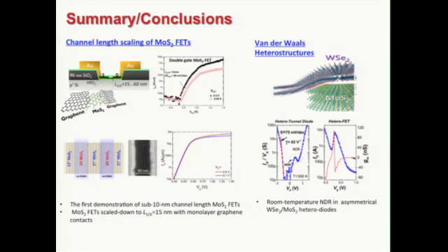I understand why the silicon curve is very steep as a function of channel length. Why with 2D material does it not? Because here, the point is that in bulk semiconductor, the dominant process is not the phonon, it is the dangling bond at the surface. So when you make it very thin, you don't have enough bulk states anymore. Everything is right on the surface. And at the surface, you have unsaturated or dangling bonds. These are scattering sites, so that would dominate the transport. But in 2D material, in a perfect 2D crystal, you don't have dangling bonds on the surface. So that's why it's less sensitive to thickness.